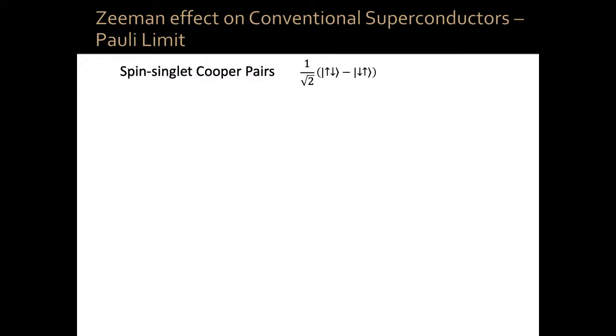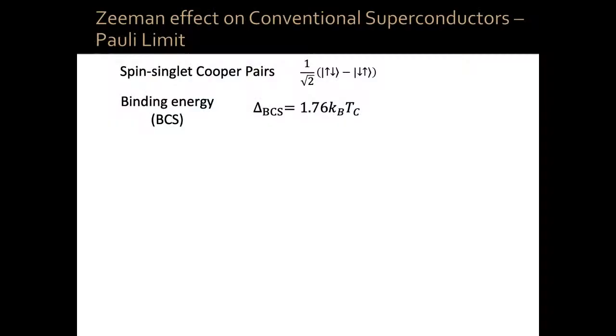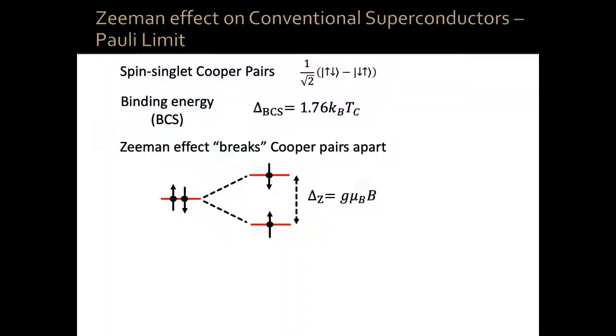Now, in a conventional superconductor, Cooper pairs are entangled states of spin up and spin down. Yeah? Now, in a conventional superconductor, you have the binding energy, the superconducting gap in BCS theory, given by this formula, which is proportional to Tc, the critical temperature. When you apply a Zeeman field, because you split spin up and spin down, by the time your Zeeman splitting is equal to your superconducting gap, you have destroyed superconductivity. Yeah?